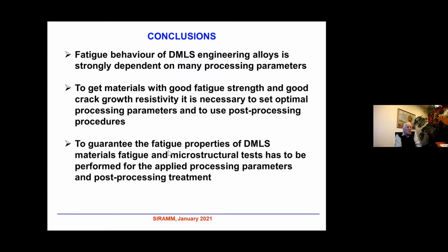I would like to conclude that fatigue behavior of direct metal laser sintered engineering alloys is strongly dependent on many processing parameters. It is nothing new, but nevertheless, it has to be kept in mind. To get materials with good fatigue strength and good crack growth resistance, it is necessary to set optimal processing parameters and to use post-processing procedures, which is not an easy task. And to guarantee the fatigue properties of direct metal laser sintered materials, fatigue and microstructure tests have to be performed for the applied processing parameters and post-processing treatment. So thank you very much, and that's all from me. Thank you.